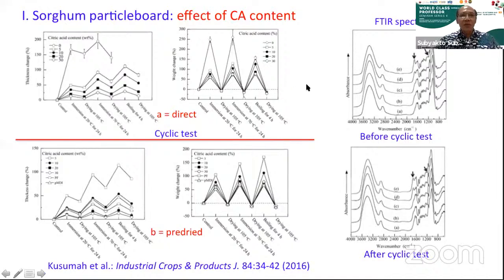And we also do the cyclic test. So this is a kind of very extreme treatment. So we boil and so on, and we can see here this is thickness change and this is weight change. We can see here that the direct method compared to pre-dried is better. This is the FTIR spectra. This is just to show that the ester linkages are formed.